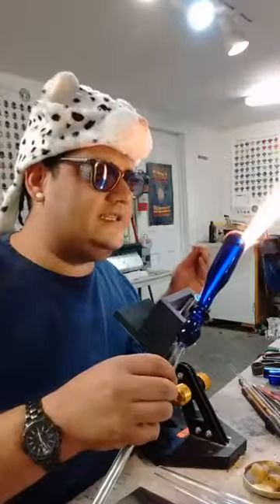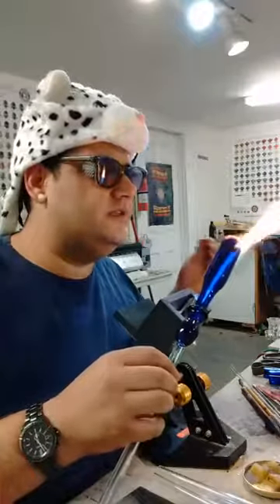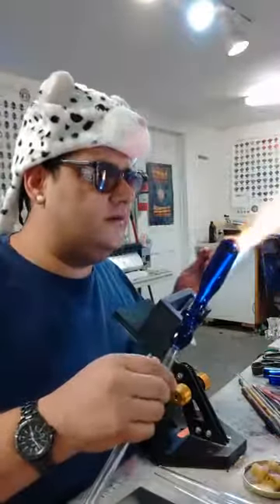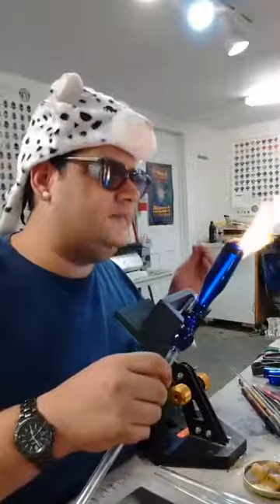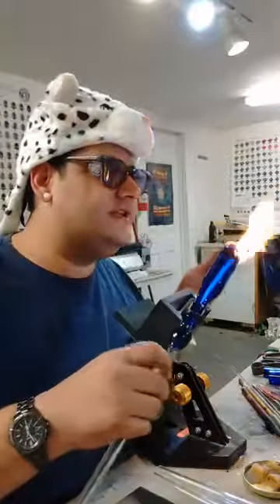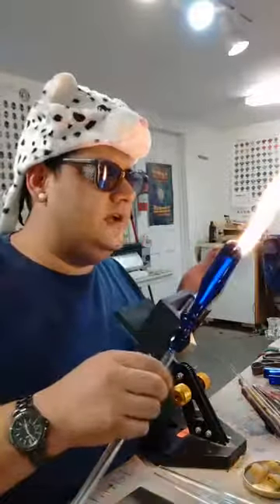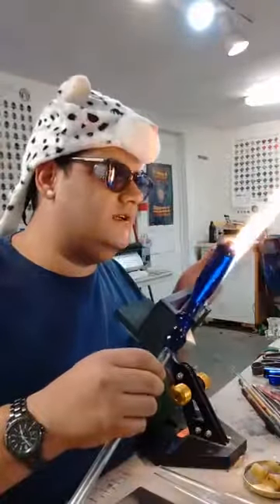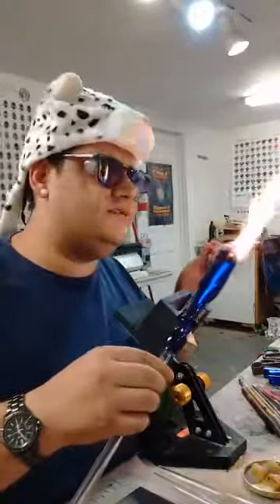Generally what I do at the very last step is flame strike my amber purple honeycombs, and I'll gauge it as I go to see where the color is. I really like the purples that you get out of amber purple, so I'll see where my purples are at, see where the depth of the honeycomb is, and go from there. You can also strike this color in the kiln, if you were wondering. I believe a good striking temperature is somewhere in the range of 1150 degrees Fahrenheit.